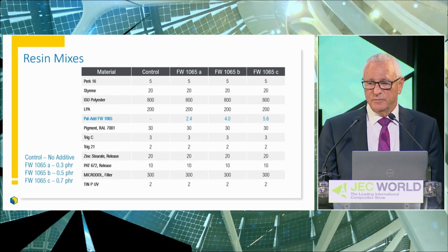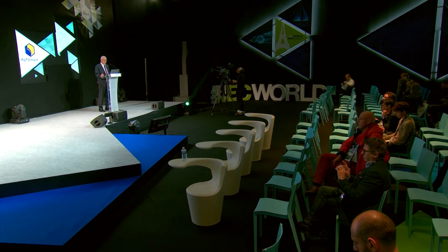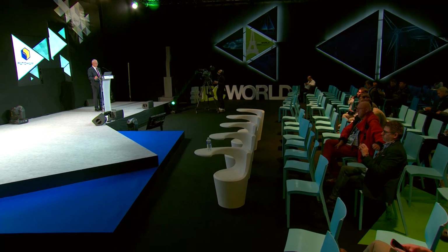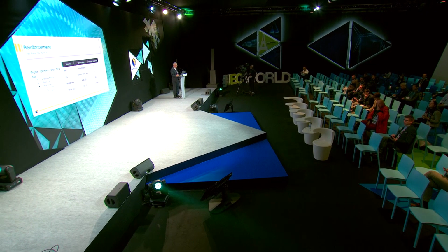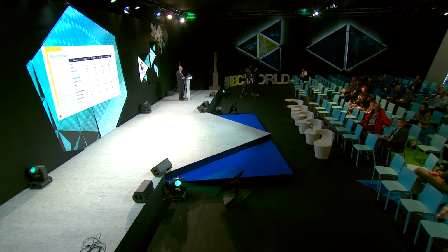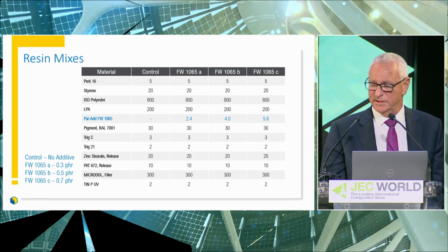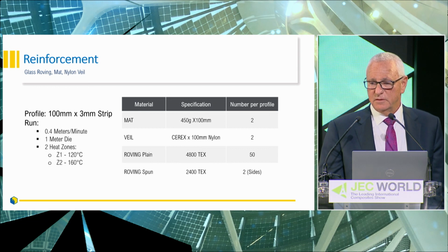These are just the resin mixes. The control resin had no additive whatsoever, and then 0.3, 0.5, and 0.7 of the Pat-Add FW 1065. The profile we ran was pretty simple, a 3 millimeter by 100 millimeter. We ran it at exactly 0.4 meters per minute through a 1 meter die at 120 and 160 for the 2 heating zones. If you go back to the resin mixes, there's Trig C and Trig 21 in there, and then Perk 16. So there's three peroxides in there. Fairly simple profile. We had a top and bottom mat and a top and bottom veil, 50 strands of 4800 tex, and then 2 woven up the sides.